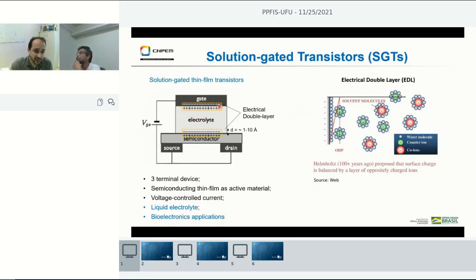So in this case, cations will accumulate at the interface with the gate electrode, while anions will accumulate in the interface of the semiconductor. And what happens in this region is that you form what the electrochemists call the electrical double layer, which means that you have a charged surface that solvated ions in the electrolyte will accumulate at very short distance from this surface, distance that range from 1 to 10 angstroms, more or less.